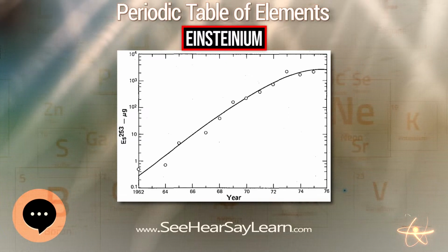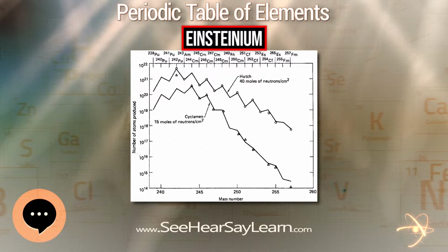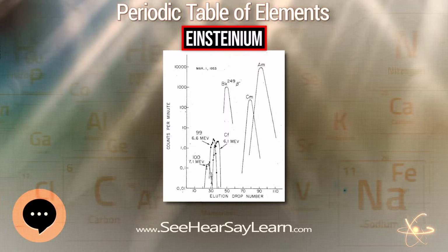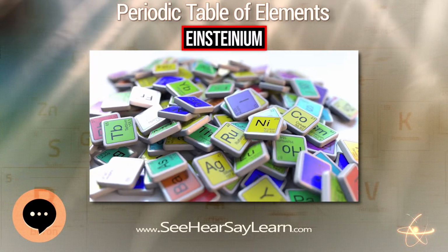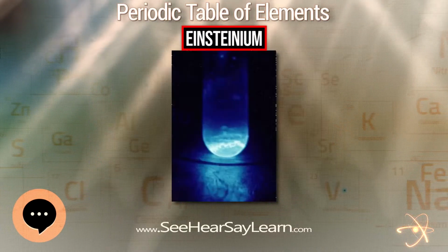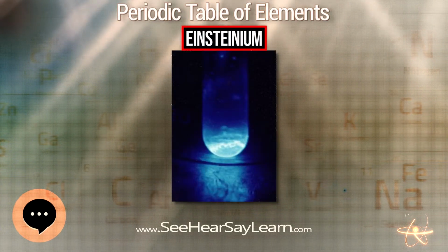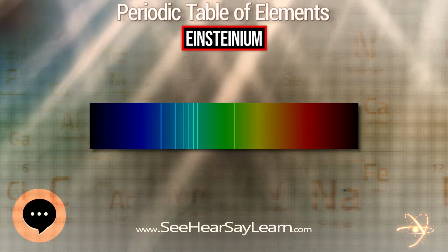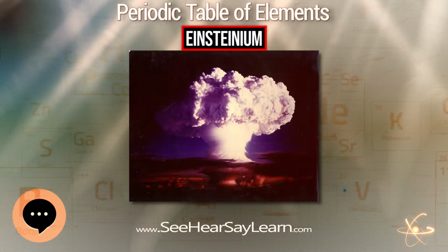Separation of trivalent actinides from lanthanide fission products can be done by a cation exchange resin column using a 90% water/10% ethanol solution saturated with hydrochloric acid as eluent. It is usually followed by anion exchange chromatography using 6 molar HCl as eluent. A cation exchange resin column treated with ammonium salts is then used to separate fractions containing elements 99, 100, and 101. These elements can be then identified simply based on their elution position/time, using alpha-hydroxy isobutyrate solution, for example, as eluent.